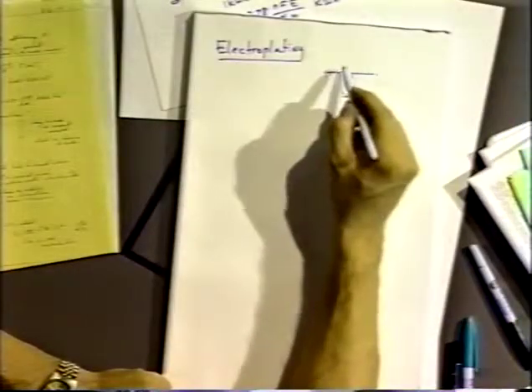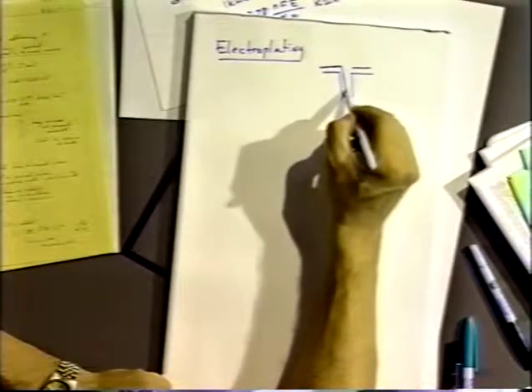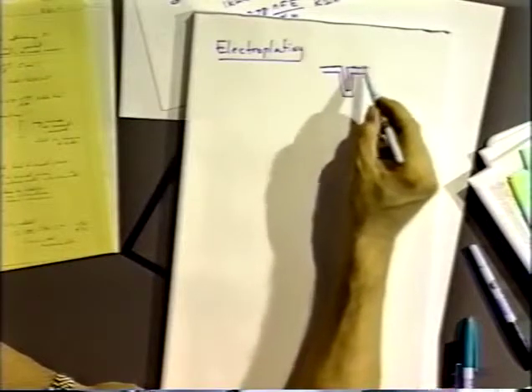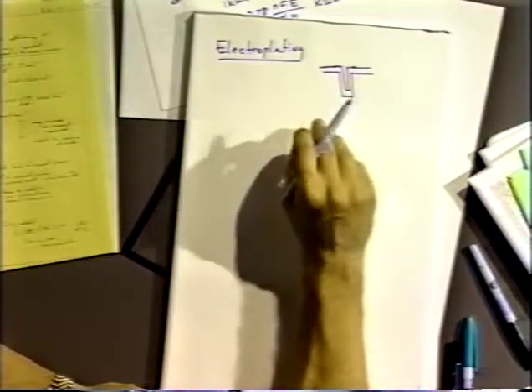The problem with electroplating is a lot of things. It's kind of still considered a craft science because there are lots of things you can adjust. For example, you have to plate usually all parts of the material, not just the surface. So if you have a crevice on the surface, you want that crevice to be uniformly plated. That means we have to make sure the overpotential or IR drop is no more inside than it is outside — and that can be very difficult. Usually what you have to do is run the reaction at less than the diffusion-controlled rate, or the mass transport-controlled rate, so you don't worry about things getting in and out of that crevice.